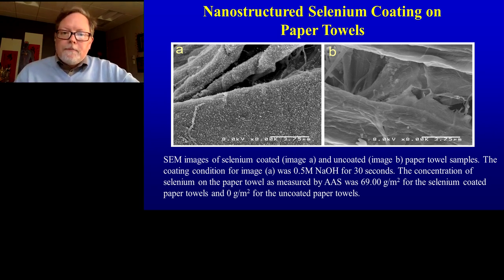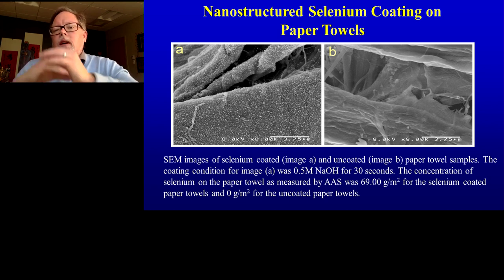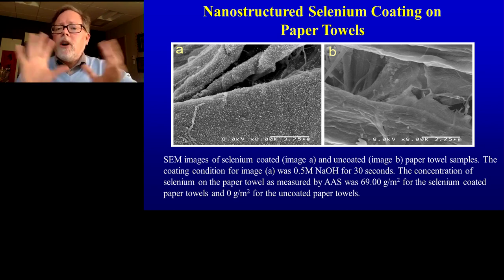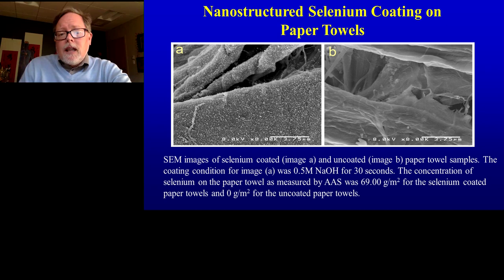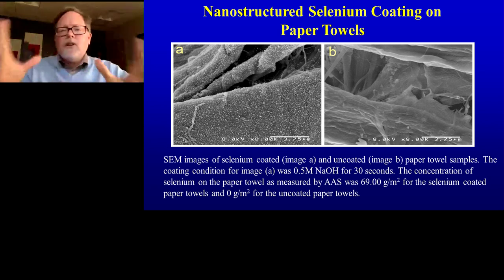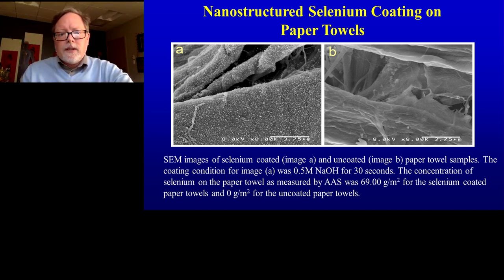So we were one of the first groups to develop a chemical reaction that can coat almost anything with selenium nanoparticles. So we're doing in the body applications, outside the body applications. Bacteria are everywhere. So we're coating a lot of surfaces with selenium. This slide shows you how we took an uncoated paper towel in B and coated it with selenium nanoparticles. So all of those little white dots in A are selenium nanoparticles. It's a simple chemical reaction. We actually have a spray. We can spray computer screens, doorknobs, you name it. We can spray these selenium nanoparticles and they stick to these surfaces.